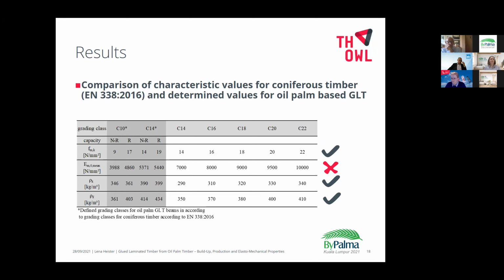The comparison of the characteristic values for strength classes C10 and C14 for GLT beams made of oil palm timber, here grayed out in the table, to the standardized characteristic values for softwood. As the comparison shows, the characteristic strength values of strength class C14 for softwood are achieved, except for GLT beams made of non-whipped lamellas of C10. Furthermore, the characteristic strength values of the whipped lamella-based beams are higher than the targeted strength classes.